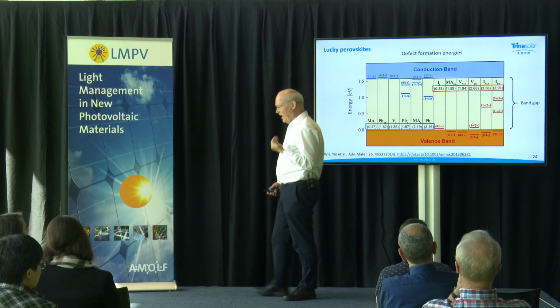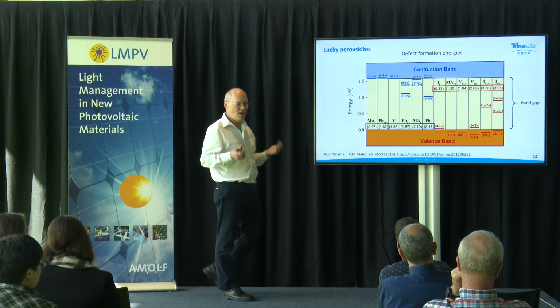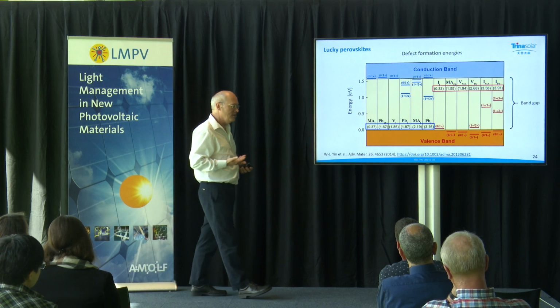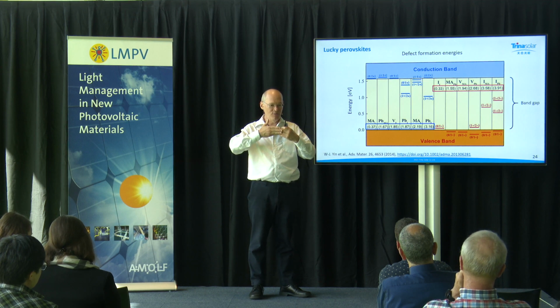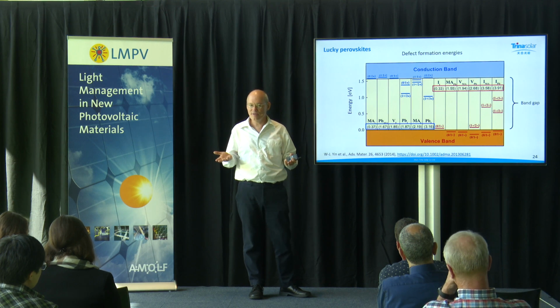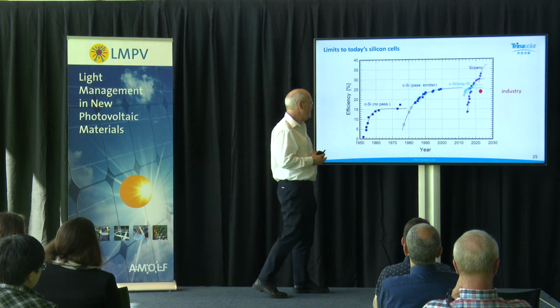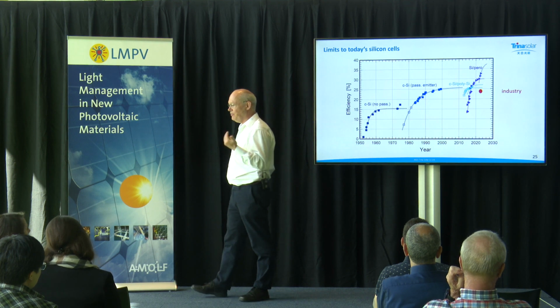That has given you a high VOC from the start, and that has actually been one of the main reasons why your material had a kickstart. You really had a kickstart, and this is because of that. If you had another material, like a highly covalent material, your defect levels would most likely be in the middle of the band gap, and you wouldn't have had a high VOC to start with. You would have had to start very slowly. This is what you actually see here. So it's important to know what is actually limiting my performance.